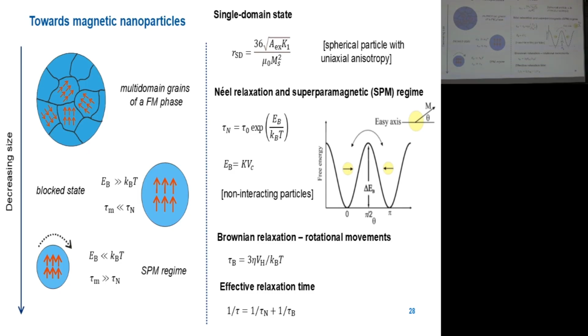And there are different techniques. So some material may appear as superparamagnetic within one technique, and it may appear blocked in another technique. In typical situations, you are studying magnetic particles with SQUID magnetometry, and the time scale of such a procedure is of the order of 10^2 seconds. If you apply Mössbauer spectroscopy, the time scale is much shorter, where this relaxation is also manifested, around 10^-7 seconds. If you apply ferromagnetic resonance, the time scale is maybe 10^-10 seconds. So then you will conclude different findings.